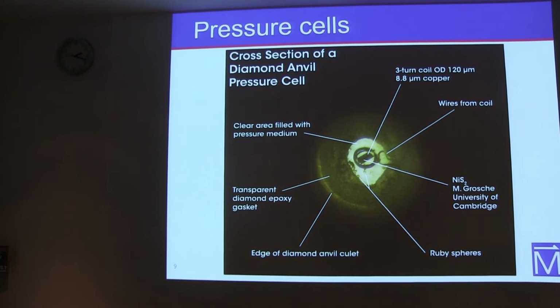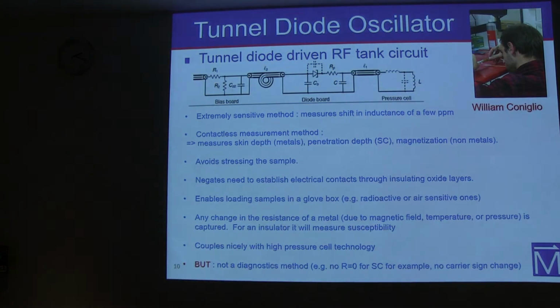So the inductor is inside the pressure chamber, or the sample chamber. And when I place the sample inside the inductor, I change the resonant frequency. Now when the sample also changes properties, when it becomes superconducting or goes through a magnetic transition, the resonant frequency also changes. So this is what we measure: shifts in frequency. And it's a very convenient method because it's a contactless method.